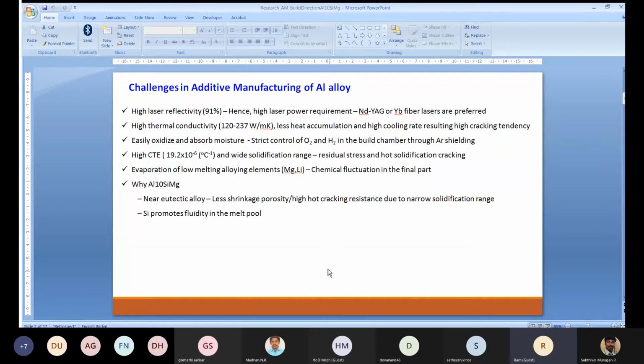Second, aluminium, like copper, has good conductivity. The problem with good conductivity is the heat in the melt pool quickly vanishes. So heat accumulation in the melt pool is very less, and the cooling rate is very high, resulting in a high tendency for cracking, especially hot cracking. Then, as you know very well, welding aluminium is very difficult because of oxidation and the stable tenacious oxide layer. So it easily oxidizes, and the powders also easily catch moisture between powder particles. So strict control is needed on gaseous elements like oxygen and hydrogen in the powder or in the build chamber, so that there will not be any problem of oxidation or hydrogen induced cracking. That's why we use argon shielding.